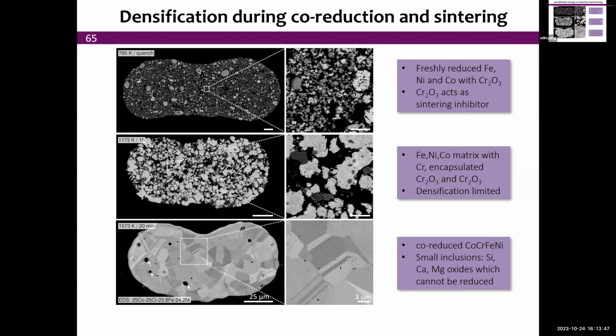In some cases, we start encapsulating. You see the dark chromium oxide particles. In some cases, at high temperature, are encapsulated. So that's game over for those. I mean, they're not going to be reduced anymore. Meanwhile, you have larger ones that are still exposed to hydrogen and will reduce. And so at the end of the day, in that particular case, we see a nearly fully reduced structure with a few tiny little inclusions.